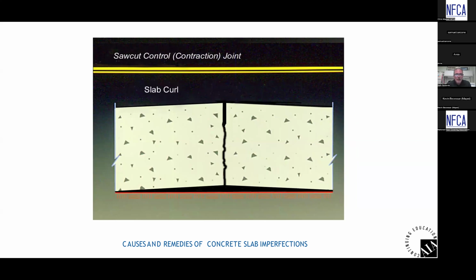So if you look at this diagram here, you will see a saw cut, cut to roughly 1/4 of the slab depth. You will see a crack at the base of that saw cut. When the concrete evaporated its water, the concrete shrank and it cracked at the base of that saw cut, just as it's supposed to do, but it experienced curl. And now the two slabs, designated by the saw cut and the crack, are up off the subbase.